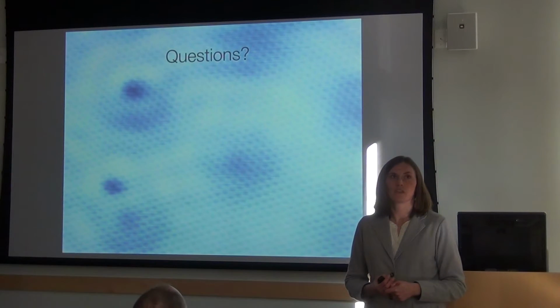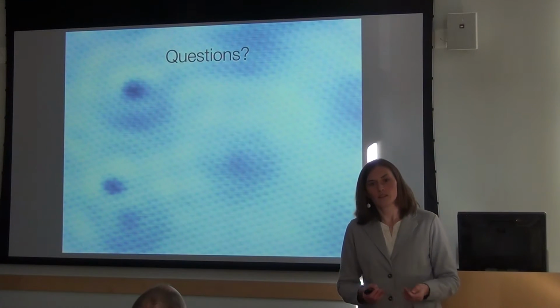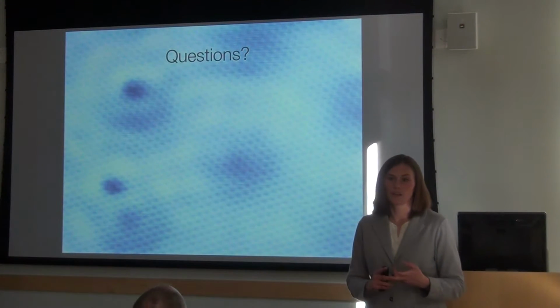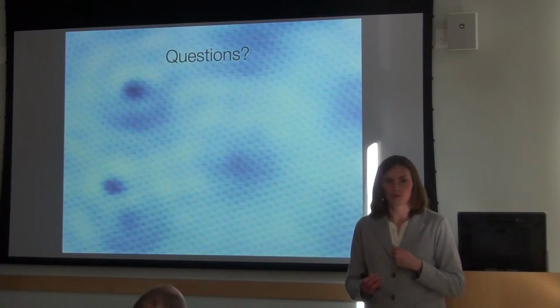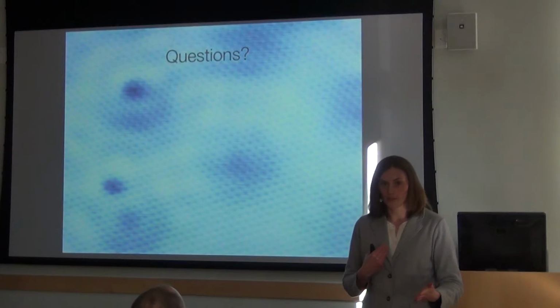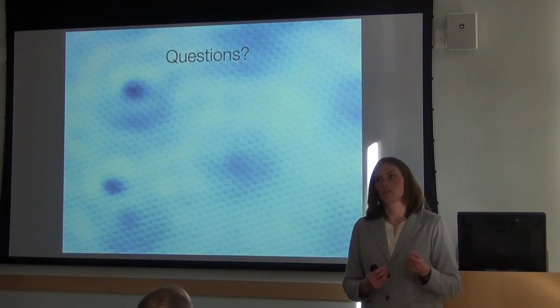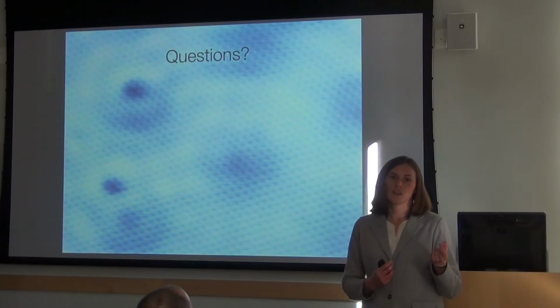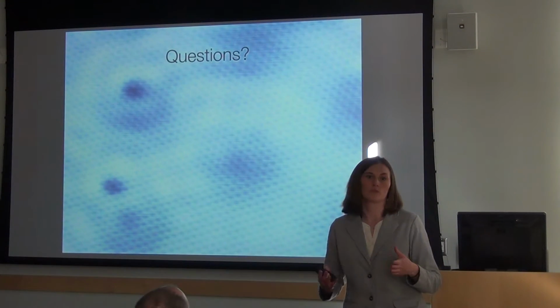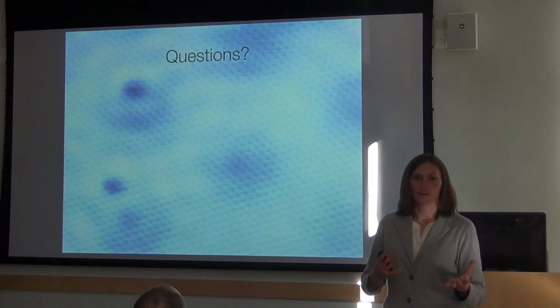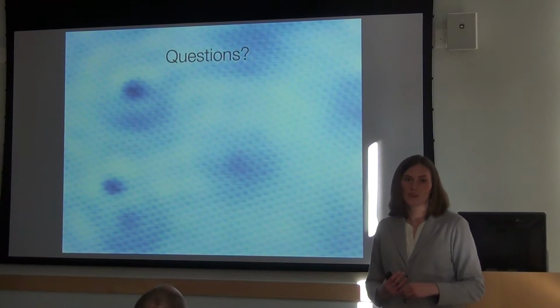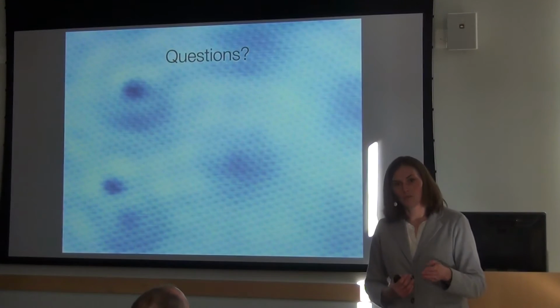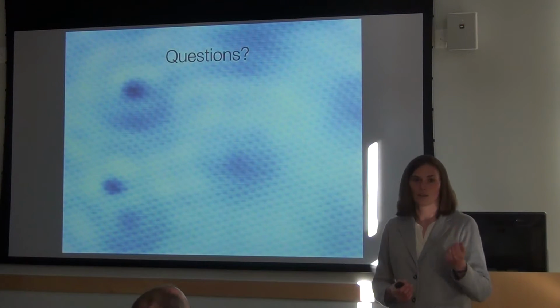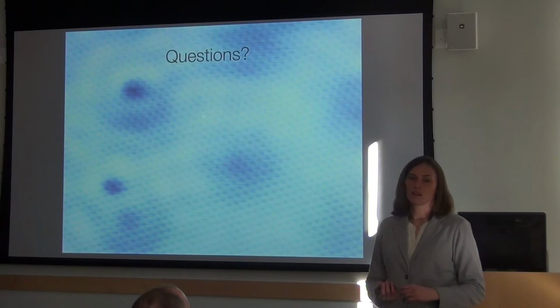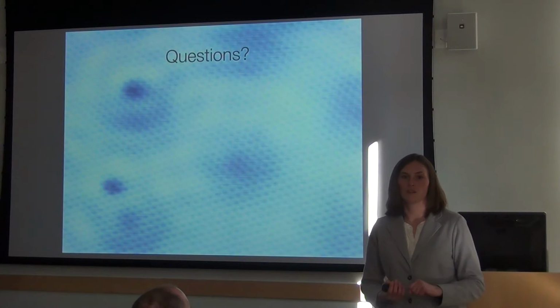Yeah, we've tried to see if there's something consistent there that's independent of tunneling voltage or tunneling current, but then you get back to this problem where you're always measuring this combination of electronic properties and topography. So if you see a change in height, you don't know which one it is. So one thing you can do is try to do DFT simulations to try to deconvolute the two. But if you don't know where the hydrogens are, then you kind of are already starting another step back. So we do see changes in the height, but they're voltage dependent. So they're dependent on the tunneling energy. And it's not clear that there's a reason to believe that it's thicker.